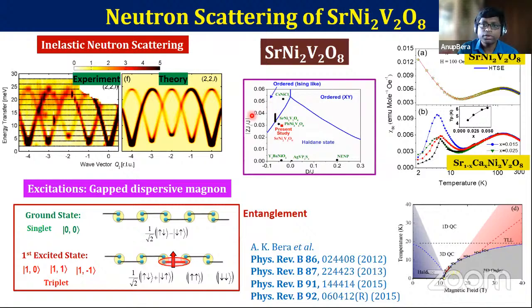Another way to introduce long range magnetic ordering is the application of a magnetic field. When we apply a magnetic field, one of the triplet states goes down and intermixes with the ground state and gives you the long range ordering. Here we have shown that when we apply a magnetic field, the Haldane state goes through this quantum critical point and shows the 3D magnetic ordering. Indeed, there are other regions which are very interesting, but I am not going in that direction today.